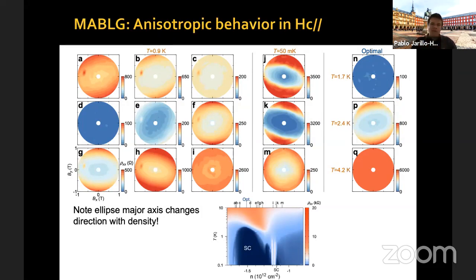there's a lot of data here, it's hard to digest all of this. All I want you to take from this is the following, which is that the ellipse major axis is oriented along different directions, as you can see here between E and G, for example, four different dopings, okay? So the system is exhibiting a twofold symmetry, but that axis, which is called the nematic director axis, is actually rotating as we change the electron density in the system, okay?